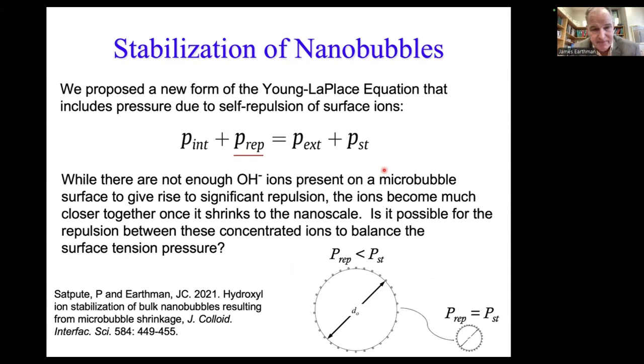But ironically and counterintuitively, if you take a microbubble and calculate how many ions it has on its surface and then shrink it by about 100 to 1,000 times, you'll find out that the ions that you start out with start to get really close together, and they start to repel each other. And so that became our theory, that it was the microbubble shrinkage itself, the thing that made it counterintuitive that nanobubbles could be stable, that actually leads to the stabilization of the nanobubble.